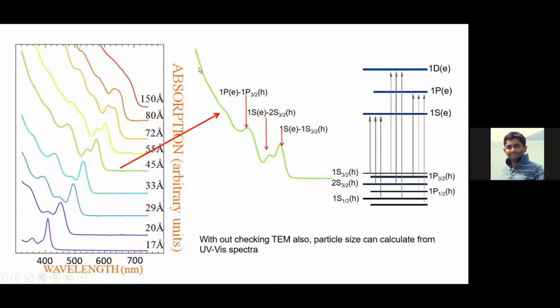And you see that this is one absorbance spectrum. It does not look like when you measure a dye, where you don't have a continuous spectrum like this. It goes down, but here, as it's a semiconductor with a continuous band, you can distinguish the different interband transitions from the absorbance. For example, here are different steps of the interband transitions, and you can see these different transitions just from the absorbance.